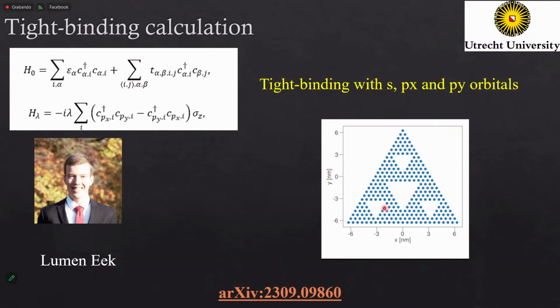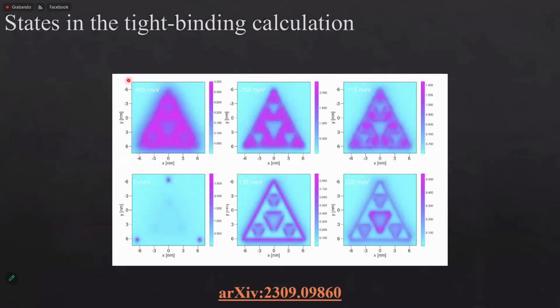In the tight binding model, basically we assume that you have electrons that are really sitting on a lattice. Then we did this modeling of the fractal lattice of the flakes that they saw. We imagine that these electrons can either hop between different sites, or they also have some on-site energy that is shown here. So doing the tight binding, you see again that this is far below the Fermi level.